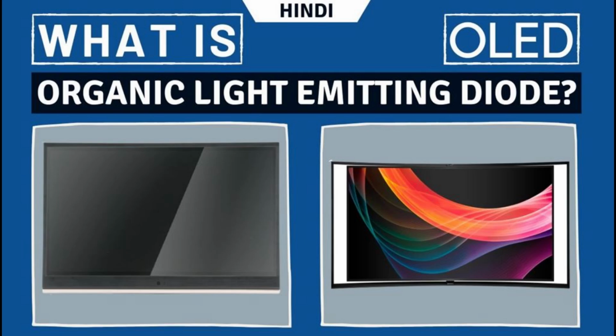Encapsulation can be performed by applying an epoxy adhesive with desiccant, by laminating a glass sheet with epoxy glue and desiccant followed by vacuum degassing, or by using thin film encapsulation, TFE, which is a multi-layer coating of alternating organic and inorganic layers. The organic layers are applied using inkjet printing, and the inorganic layers are applied using atomic layer deposition, ALD. The encapsulation process is carried out under a nitrogen environment, using UV curable LOCA glue, and the electroluminescent and electrode material deposition processes are carried out under a high vacuum.